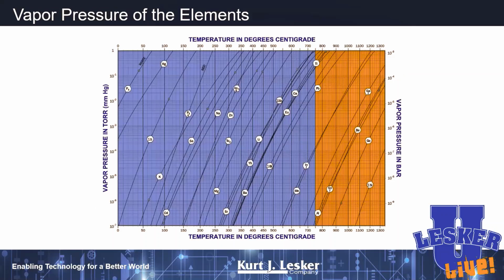If you just want to look it up, these are a color version of Rick Honig's equilibrium vapor pressure charts. Very, very handy. Unfortunately, he only did these for single element metals, so it doesn't help you if you're trying to do oxides or nitrides or sulfides. But if we're just trying to do a single element metal, let's pick zinc here. Equilibrium vapor pressure is on this axis, so 10 to the minus 4 is here, 10 to the minus 2 is here. Let's say we want to be right in the middle, 10 to the minus 3 torr. We go over to that line, and go up to the temperature line, and it says we need a temperature of about 275 C to get zinc to give us the vapor pressure that we want. Notice the melting temperature for zinc is much higher, over 400 C. So in the case of zinc, we're not going to melt the material in order to get the vapor pressure that we want. That's really nice.